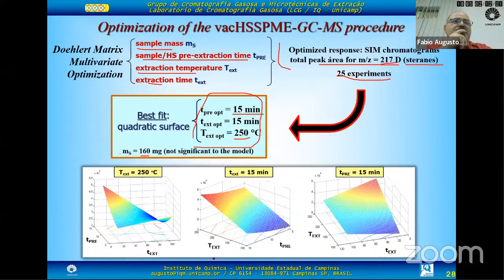And is there any way to check, beyond the kinetics of extraction, that you have reached some level of vacuum experimentally? The pump has a dial, a manometer, so we see there. Of course, after some time, when you put your sample inside the heating block, volatilization may reduce the vacuum, but for the same sample, we think that this is repeatable and comparable. And even if you use other samples, there are trace amounts of oil. In this case, we selected a sample with a very large oil concentration to be sure of it. But for most samples, the amount of oil is very, very small.